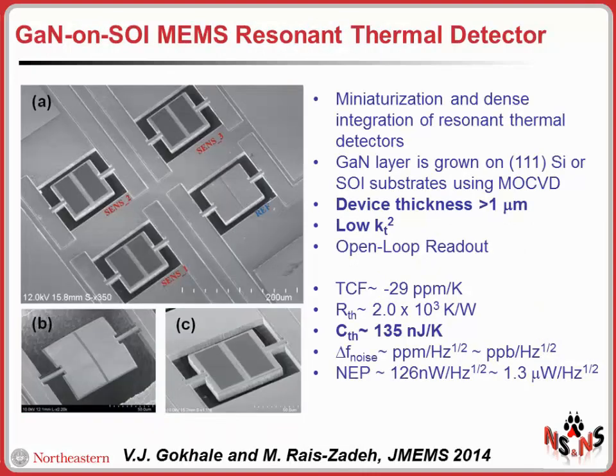More recently, some excellent work has been done also by Mina Rais-Zadeh's group at the University of Michigan. They demonstrated that further miniaturization and dense integration of resonant thermal detectors is possible by using thin film piezoelectric materials rather than a bulk substrate like quartz. They demonstrated a resonant thermal detector using thin film gallium nitride with a device thickness in the order of a micron. As you can see here, by scaling the dimension of the device, they were able to achieve thermal capacity in the order of under 135 nanojoule per Kelvin, so one order of magnitude improvement in thermal capacity. This is a smaller device. But despite this scaling, they were still able to maintain good noise performance and demonstrated noise equivalent power in the order of hundreds of nanowatts per square root of Hertz. And I think in some more recent work, they were probably able to push this down further.